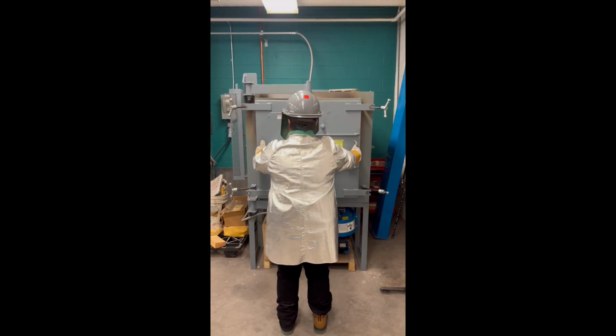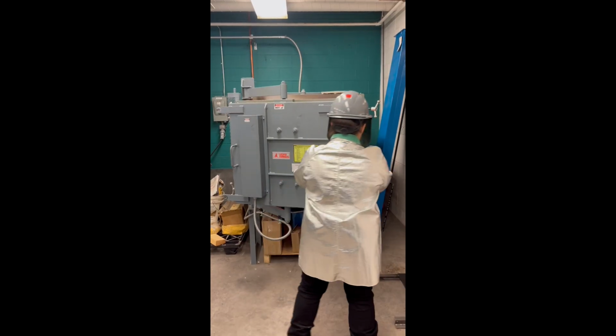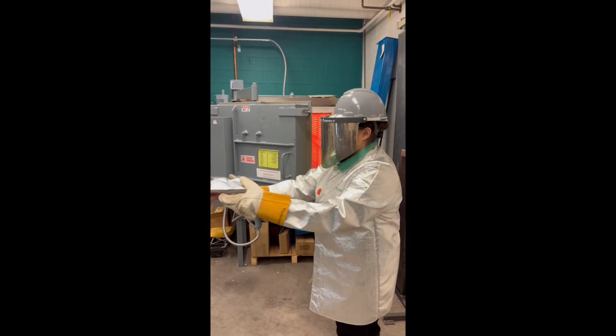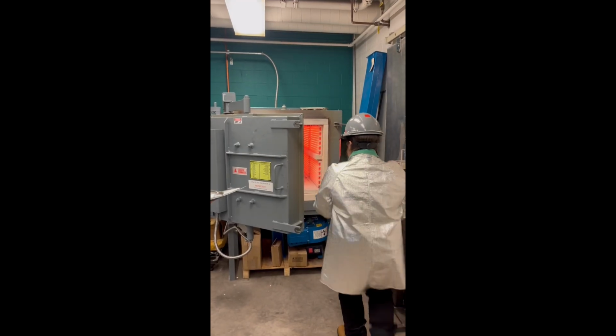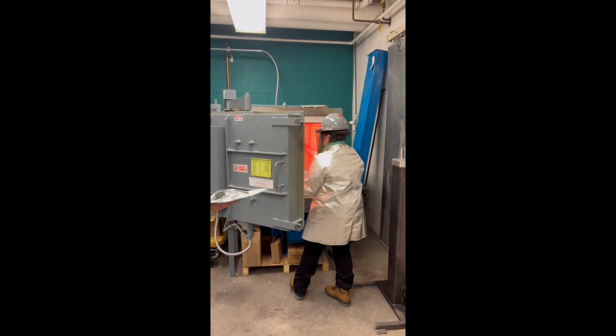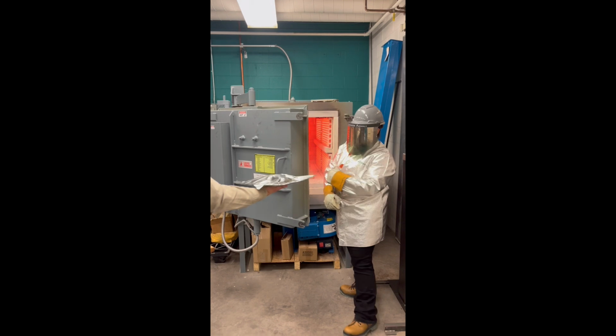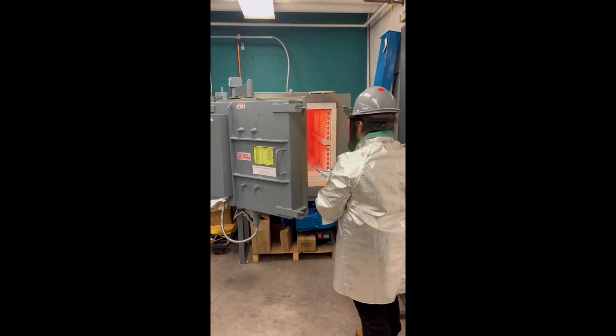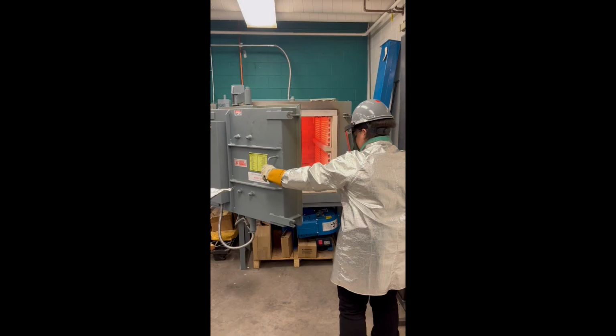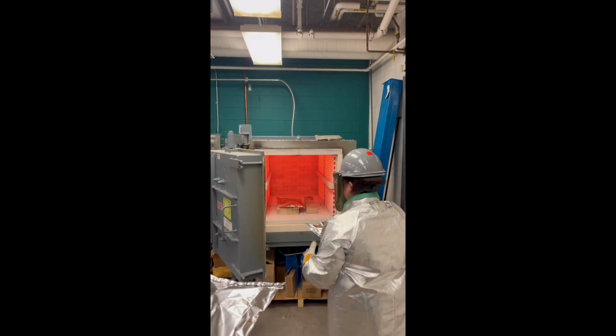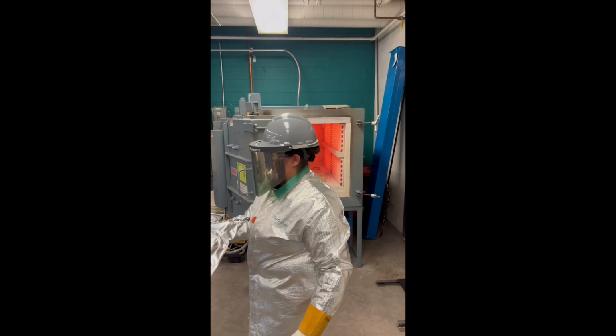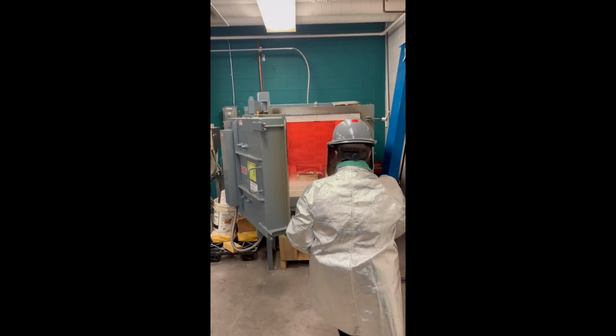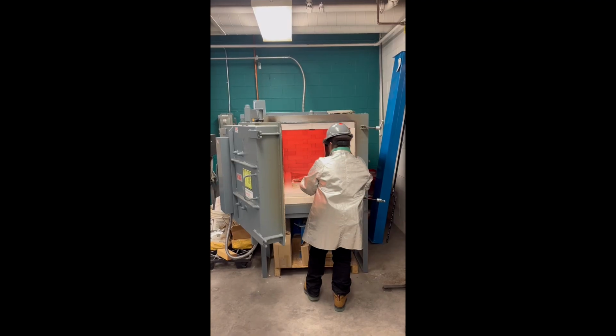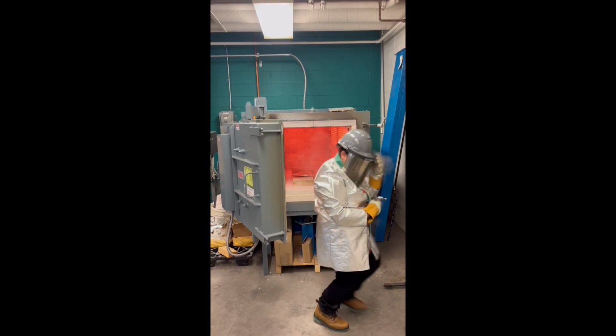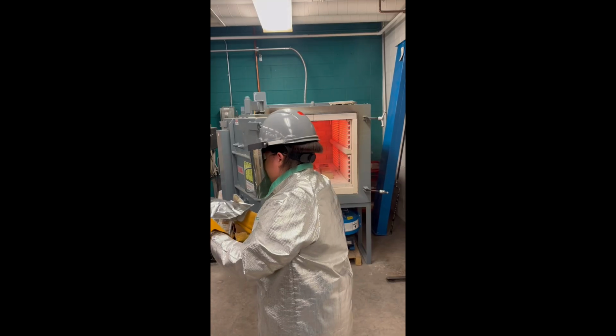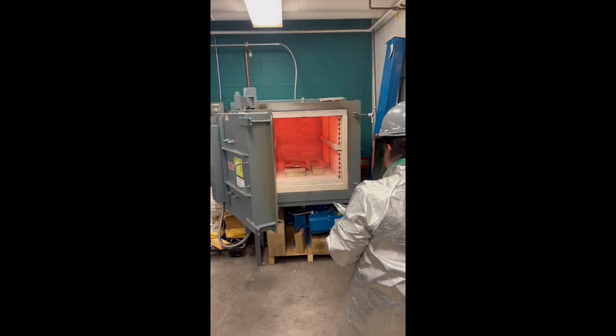For annealing, we chose to anneal because 4340 steel is notoriously hard to machine, and when we anneal, it brings down the hardness significantly, so it makes the ductility a lot better to machine with. Because of that, we ended up choosing a 1400 degree Fahrenheit heat temp for 1 hour due to the decarburizing that 4340 can face, and putting them in bags also helps prevent decarburizing. After it was put in for an hour, we cooled off the furnace to 1,000 degrees and let the axe heads go down accordingly. And then after 1,000 degrees was reached, it was air cooled.